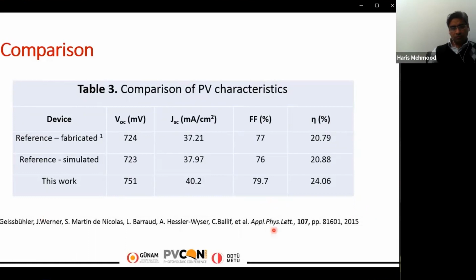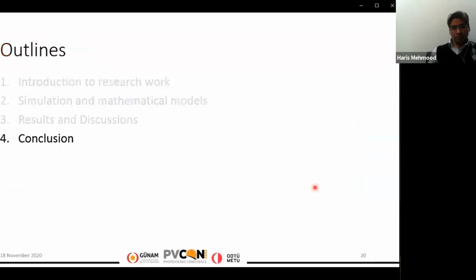So our proposed device has a better open circuit voltage because of the large work function of tungsten dioxide equal to 751 millivolt, and the better current density, better fill factor, and better conversion efficiency of 24.06%.